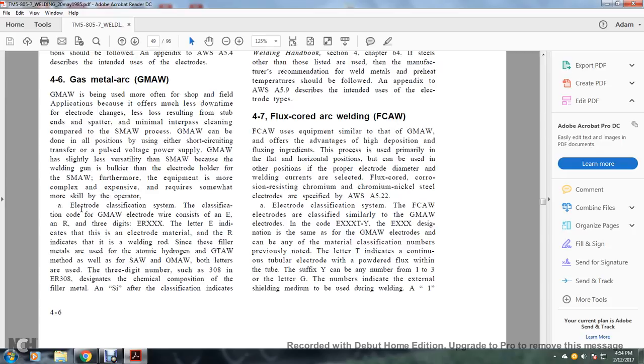Electrode classification system. The classification code of the gas metal arc welding wire consists of an E and an R, followed by three digits. The E indicates the electrode material. The R indicates that it is a welding rod. The filler metals are used with shielding gas.